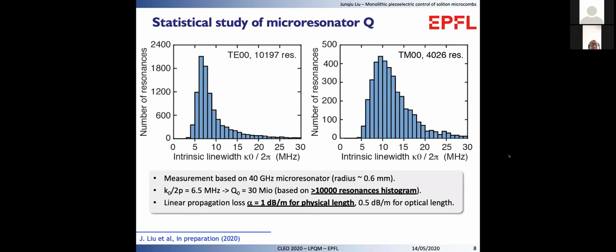To fully characterize the loss of our integrated microresonators, we measure the resonance line width of many resonances, more than 10,000, and analyze their statistical distribution. As shown here, in a 40 GHz FSR microresonator, we have achieved 6.5 MHz intrinsic line width as the most probable value, which corresponds to an intrinsic Q factor of 30 million. The 30 million Q value corresponds to 1 dB per meter loss.